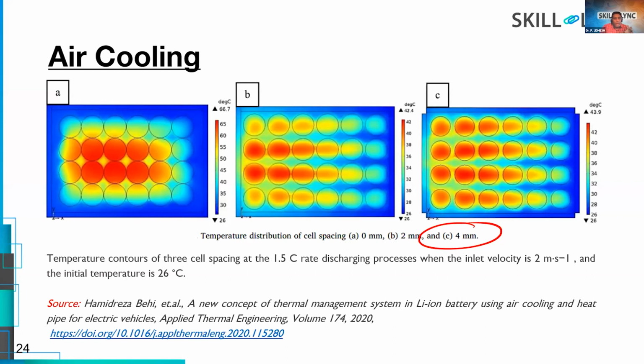So there is a porous media, right? You have to optimize the space between the batteries so that we can maintain a uniform temperature, and not only a uniform temperature but also a lower temperature. So always remember that delta T should always be less than or equal to 5 degrees Celsius. Delta T is the temperature difference between the batteries. In this case, they have used this spacing to study the temperature distributions.